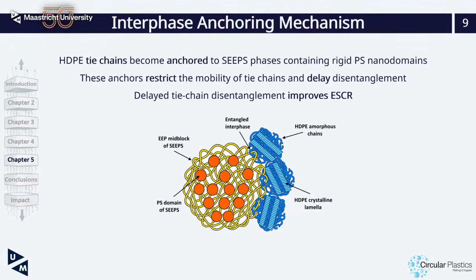Based on these observations, we propose the interphase anchoring mechanism to explain why adding SEEPS significantly improves ESCR. According to this mechanism, amorphous HDPE chains, including the tie chains, become anchored to the SEEPS phase that contains rigid polystyrene nanodomains through the entanglements in the interphase. These anchors restrict the mobility of the tie chains and delay their disentanglement, because environmental stress cracking is strongly governed by these tie chains and their disentanglement. Delaying this process improves resistance to slow crack growth and environmental stress cracking.